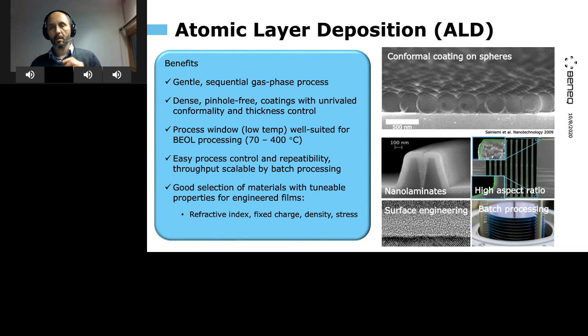For CMOS image sensors, the ability to control materials is very important. We have a few nice oxides and nitrides, and we can flexibly mix and laminate them to produce desired and targeted properties — for example, refractive index, specific charge of the film, density, and stress. These little berries on the plate you see are a few hundred nanometer sized polymer spheres coated with aluminum oxide — you can see the coating is conformal. The nano-laminate pictures show two oxides, high and low index, running conformally around nano shapes, demonstrating the same coating thickness at the top of a trench and at the bottom.